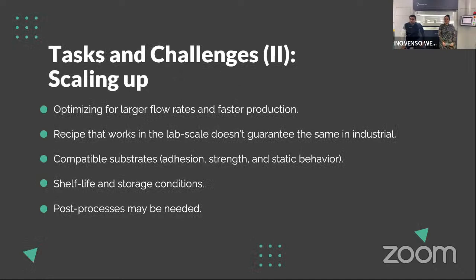So let's talk about scaling up. This is where the real fun begins, because we have to talk about a lot of parameters and a lot of things you need to consider when optimizing for commercial scale filters. When you have a prototype at lab scale, it might work well for one single needle perfectly fine. But when you use multiple nozzles, or even switch over to an open surface system, you'll find that you can't just copy and paste the recipe, or rather the operational parameters. You would need to adjust them, of course.